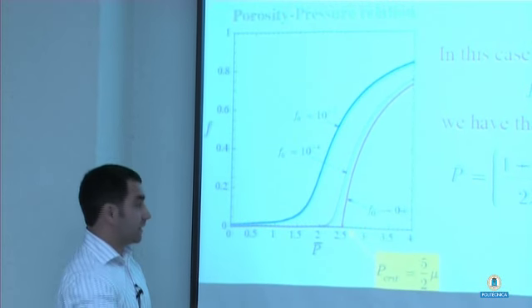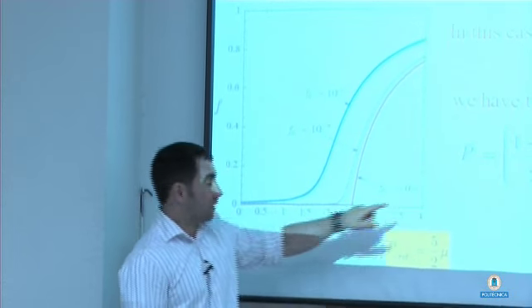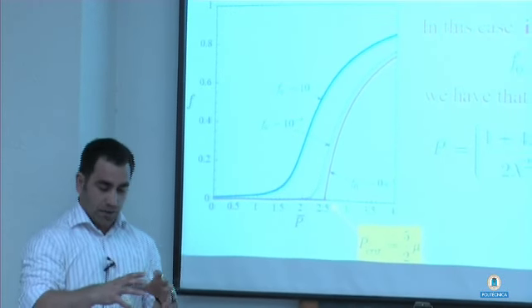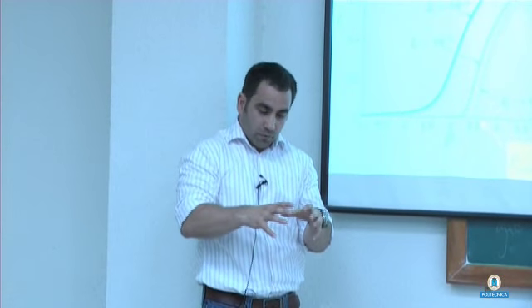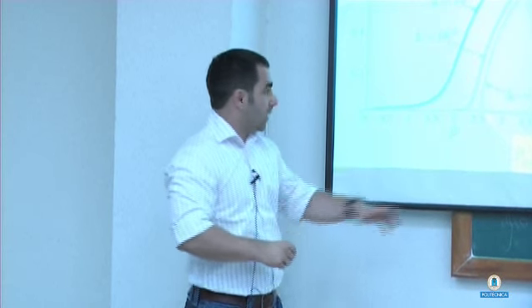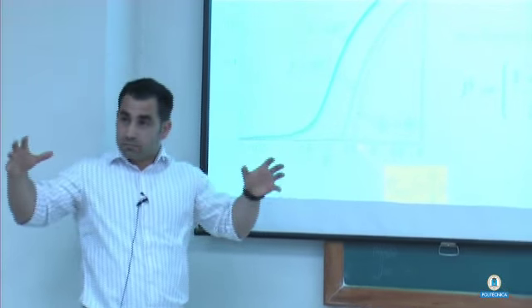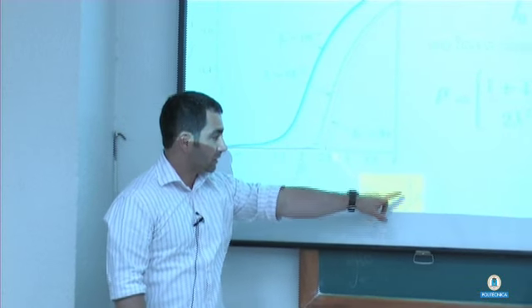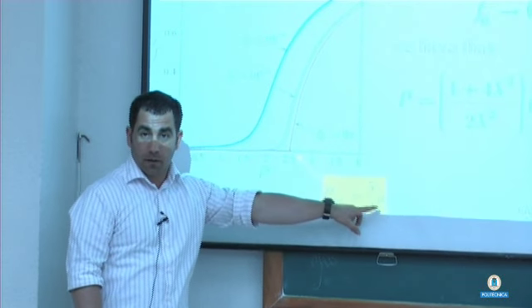Eventually, if you go and take the limit of F naught goes to 0 plus, what happens is the porosity remains 0 all the way. So you apply pressure, the thing is not moving. Of course, it's incompressible, right? Not moving, not moving. There's a critical pressure at which the porosity starts to grow, right? And the critical pressure for a Neo-Hookean material under this type of loading condition is 5/2 mu, all right?